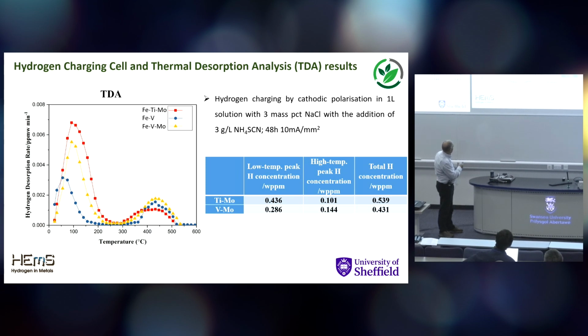So there's a big peak down the bottom, and then there's another peak at higher temperature. The lower peak is associated with trapping in dislocations, grain boundaries, martensite lath boundaries, and so on. And trying to separate out which of those is important is really quite tricky. In our case, we did it through some atomistic modelling, but there's a lot of debate about that. The higher temperature peak here is the deep traps, the irreversible traps, and those are the ones that are associated with the precipitates.